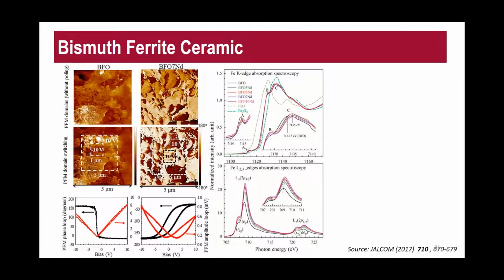This is another BFO, and another result to show by comparing BFO versus BFO 7% Nd. This is to show how important it is to have this PFM analytical tool to identify the behavior of the materials, because we can see BFO has a very huge leakage, and that is why the behavior of the hysteresis loop as well as the amplitude is different compared to 7Nd. And 7Nd having this also indicates that the leakage has been improved. All right. We also make use of the X-ray absorption spectra to prove the observations that we've seen in PFM2.